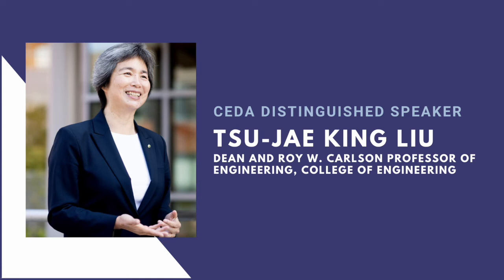That's a great question, very commonly asked, actually. My group originally worked on mechanical switches for logic, for computing, so we did look at endurance challenges. Part of it is highly dependent on the contact material. The switches I showed here have tungsten as the contact material because tungsten is a refractory material. It's hard, it doesn't wear out mechanically. And what we found, in accelerated lifetime testing, is that if you force a voltage difference between the source and drain, even when they're in contact, that will cause joule heating, and eventually welding, so the switch stays stuck shut.